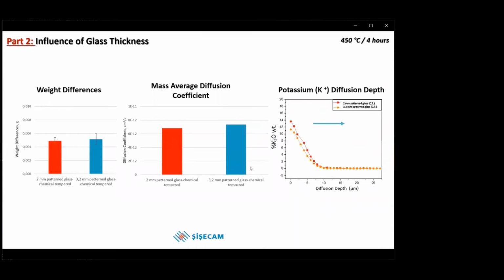In this part, 2 and 3.2 millimeter patterned glasses were compared in terms of the weight differences before and after chemical tempering, the diffusion coefficients, and depth of potassium ions into the glass. In the first graph, it was shown that the weight difference values for the 3.2 millimeter patterned glass samples after chemical tempering were higher than the 2 millimeter patterned glass sample. It was observed that there was no significant change in diffusion coefficient values. Potassium diffusion depth of 3.2 millimeter thick patterned glass was found to be slightly higher than 2 millimeter patterned glass.